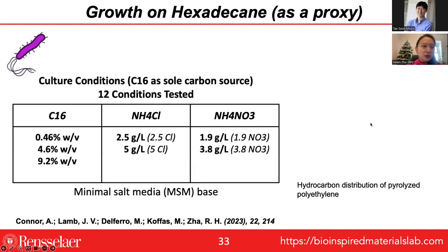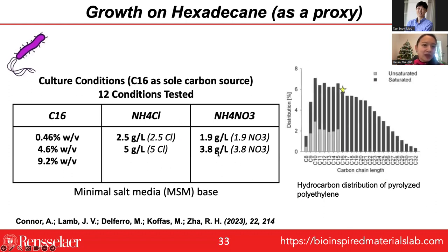So we looked at using C16, which is hexadecane, as a proxy for what you get out of pyrolyzing polyethylene. And we tested a variety of conditions, basically trying to optimize the media composition here. We tested several different nitrogen sources, ammonium chloride, ammonium nitrate. And C16, by the way, is one of the most prevalent compounds you'll find coming out of pyrolyzed polyethylene. So we use that as a proxy system for our studies to begin with.